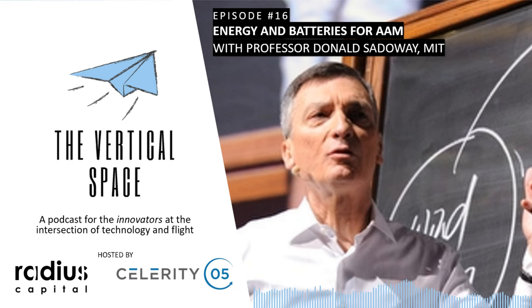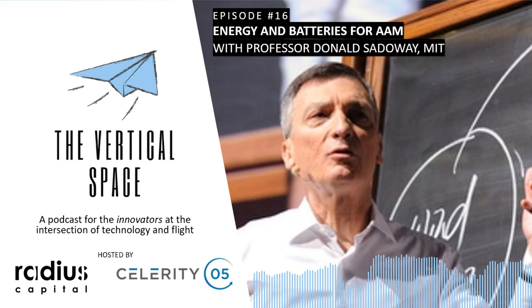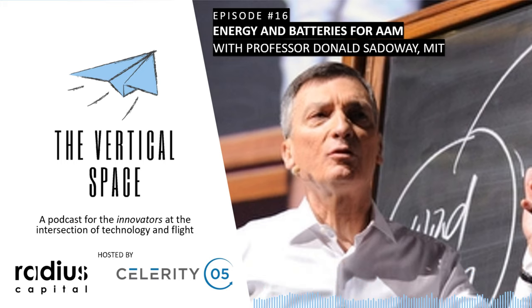When I gave that talk back in 2012, we thought we were going to go to larger and larger. I talked about the shot glass and the hockey puck, which is about 3 inches in diameter. And then we're going to go to the saucer, 6 inches in diameter. Then we're going to go to the pizza and so on. And then we're going to the bistro table. Well, it didn't happen that way. We very quickly came to the realization that the unit cell shouldn't be too big. It shouldn't be too small, but we were way over our skis on that one. So we learned a lot in the interim. No, everything else is pretty much correct.